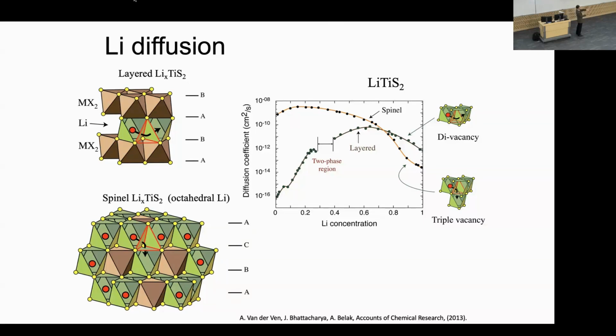So what that means is when the C lattice parameter drops, the interlayer spacing decreases. And this site, which is where the lithium hops through when it goes from one octahedral site to another one, gets crunched down much more rapidly than the initial site. And so the migration barrier increases by 100, 200, maybe even 300 meV. So it's an enormous effect.